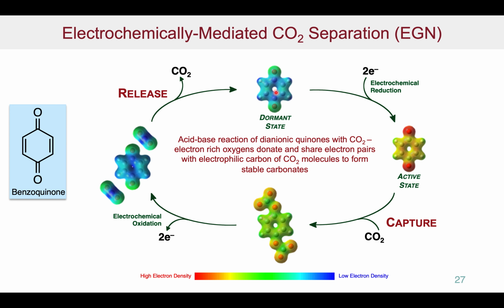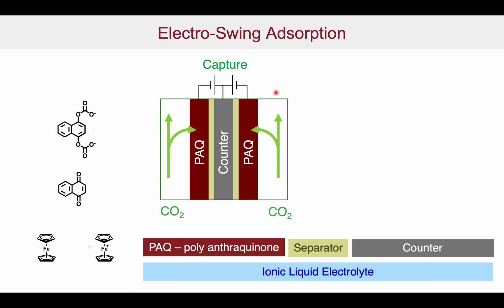Now, we've done some work looking at a new type of approach, electro-swing adsorption kind of operations, as opposed to having these quinones in solution. What we do is we take the quinones and we immobilize them on an electrode substrate. So this is the quinone immobilizing electrode substrate, anthraquinone in this particular case. And then we need a counter electrode to be able to complete the circuit. In this case, we used a ferrocene counter electrode. We had this particular kind of configuration, and this whole thing is bathed in ionic liquid electrolyte to provide the ionic current and be able to close the circuit.